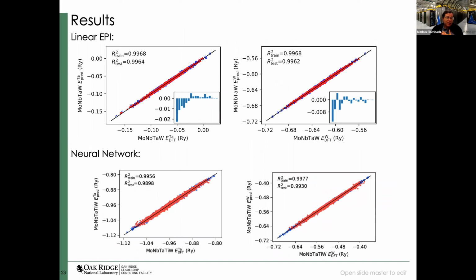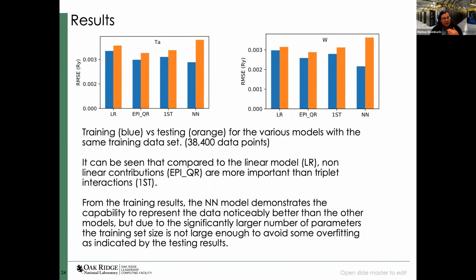For these refractory alloy models we've looked at in this work, it turns out that actually this linear pair interaction model gives somewhat better model prediction, and that is mainly due to a much smaller variation. This is mainly due to the fact also that the neural network has many more parameters, so significantly larger data sets are needed to train them sufficiently without, again, the risk of overfitting. Again, that is supported here.